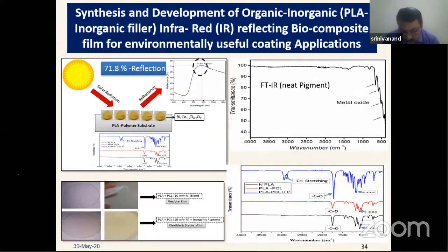And similarly, since PLA has found a lot of application, we thought of incorporating some inorganic pigments, because as I told you, the bio-based polymers are nothing but a combination of synthetic polymer and bio-based polymer, where the maximum portion is bio-based polymer only. So I have 90% bio-based polymer, whereas I can go up to 10% synthetic material. Keeping that in mind, we started incorporating an inorganic pigment which is capable of reflecting the IR radiation and resisting the UV radiation. So we have made an IR-reflecting coating using such inorganic pigments.